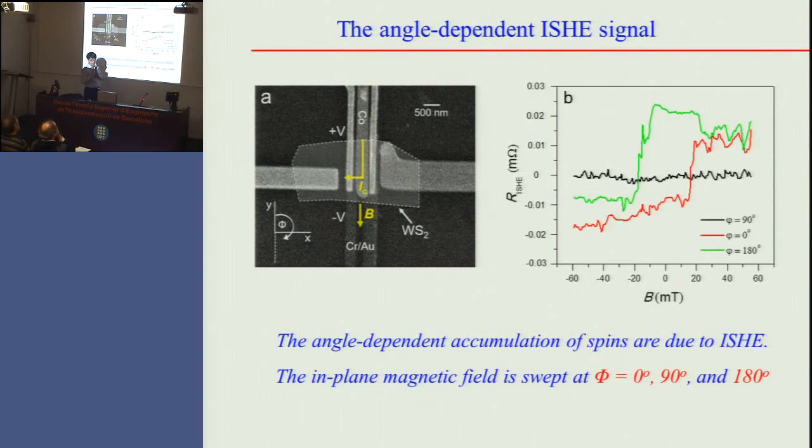So depending on spin orientation, the detection terminals of the inverse spin Hall effect should be chosen correctly. Here, since the spins are aligned that way, your detection should be top and bottom. If you align the spins that way, there is no deviation of electrons by the inverse spin Hall effect. With such a test experiment, you can prove your measurement is really from the inverse spin Hall effect. This is the proof of that.